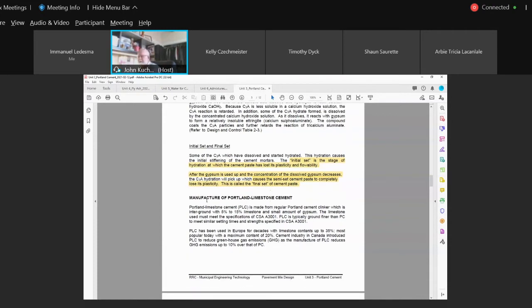Okay, we have a cement out there now that we're taking Portland and blending it with limestone dust. And a lot of the limestone dust that you had in the crushed limestone aggregates, or Carsey, exceeds the minus 200 criteria. We need 0 to 1%. You can go up to 1.5% if that additional 0.5% is not clay.